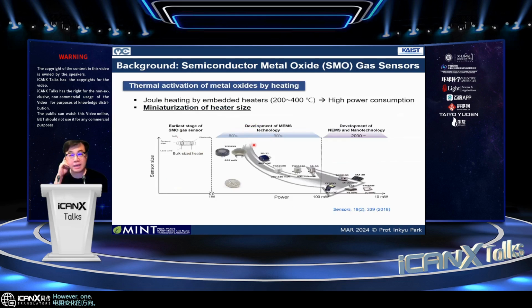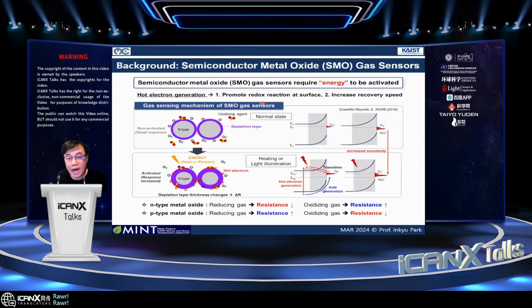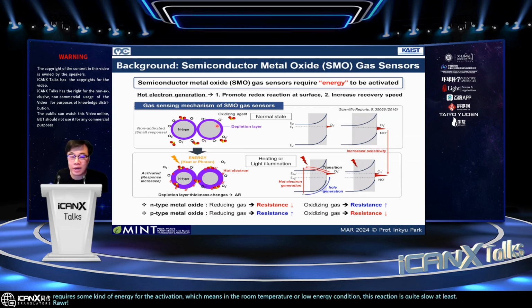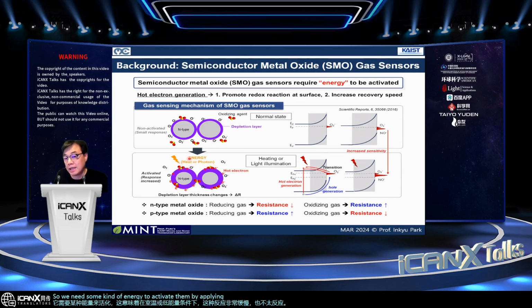However, one of the drawbacks, I would say, is that it requires some kind of energy for the activation, which means in room temperature or low energy condition, this reaction is quite slow and also not quite reactive. So we need some kind of energy to activate them by applying some heat. We're talking about temperatures above 200 or 300, even 400 degrees Celsius. Quite high temperature is needed to heat these semiconductor metal oxide materials. Also, we can activate this by shining light, which I will talk about later.